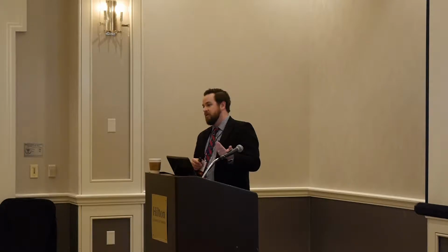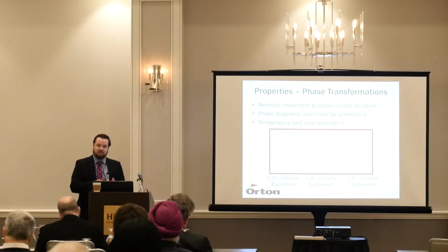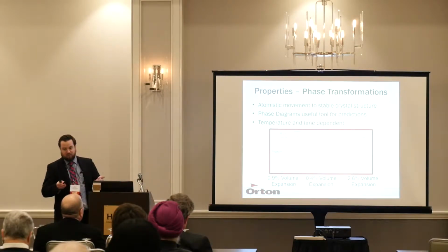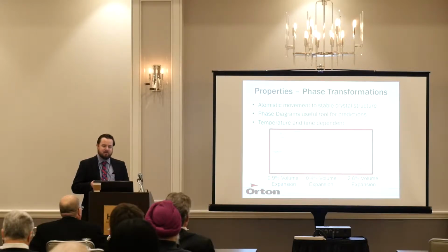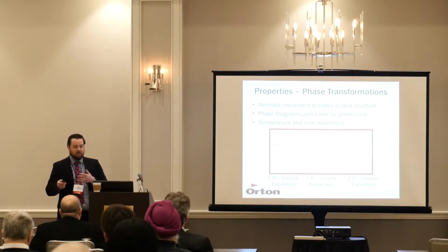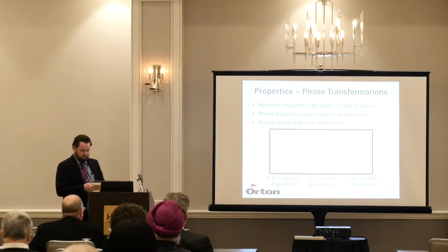So now when you run the dilatometer and you get your CTE and your actual permanent linear change, you can see, in fact, it's at 573, how much material is quartz? You can start to calculate that based upon what the volume expansion would be if it was purely quartz from high to low. So those start to show you the complexities that you can use the dilatometer for. At the same time, this is more common in the different industries where you have a lot more phase transformations occurring. But don't let that deter you. It is a very powerful tool.